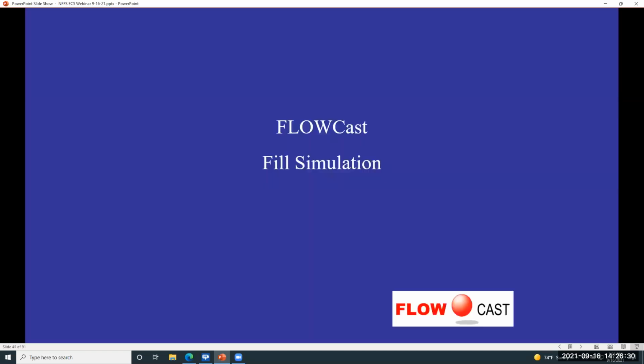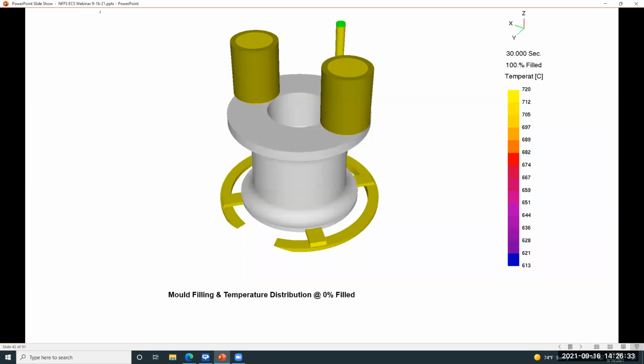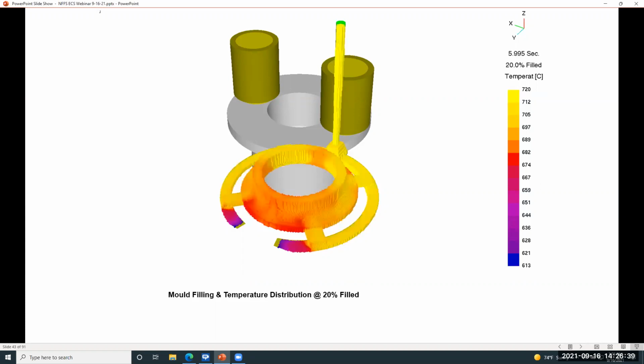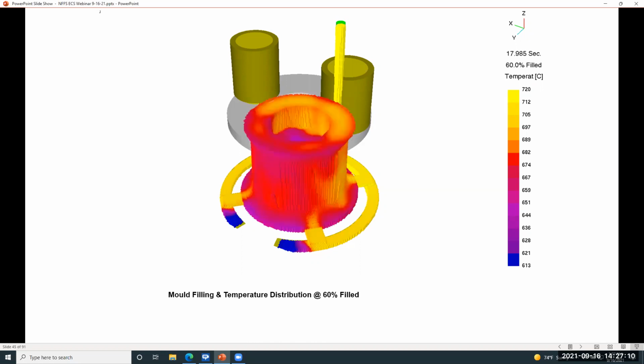Just another view. And here we're going to see a couple of screenshots showing the filling process. This shows a 20% increment. We're looking at the temperatures that are changing during the filling process. And if we broke it down and created a movie, we would be able to see the entire filling process in a smooth, real-time sort of fashion, so that we could see if there's any splashing or formation of areas where gas would be trapped, things like that.